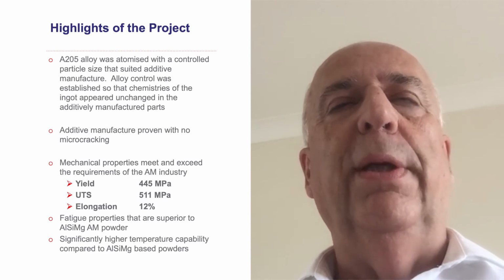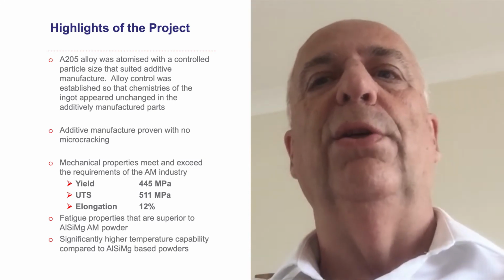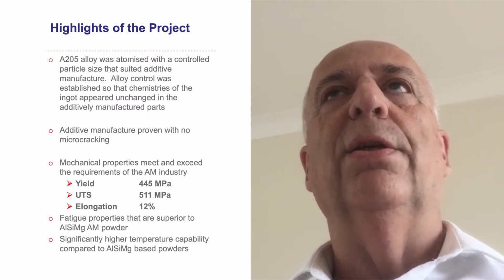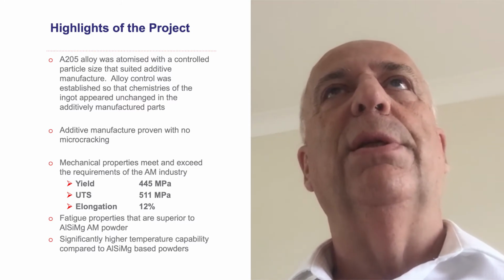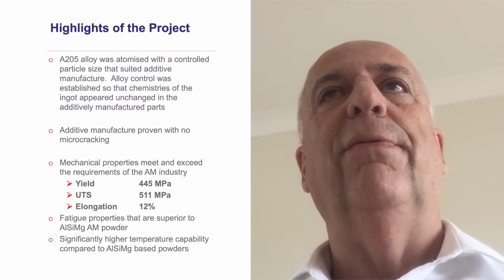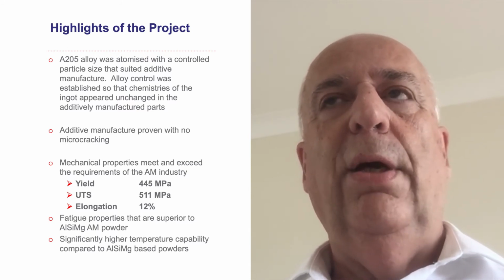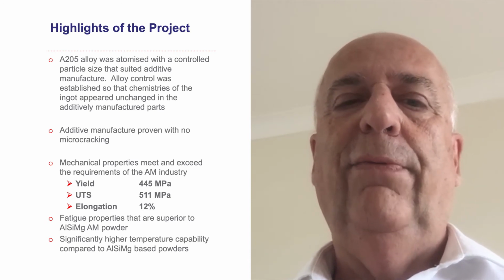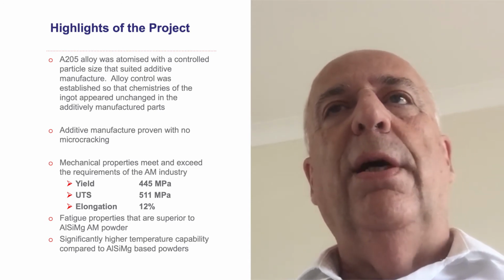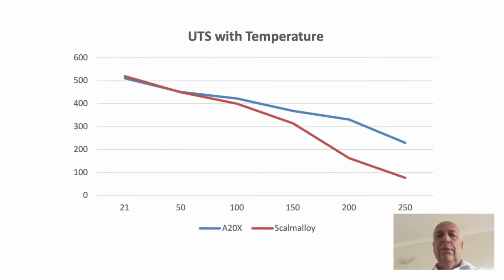And the fatigue properties that we achieved, which were measured by Rolls-Royce, were actually greater than aluminium, silicon, magnesium, the standard additive manufactured aluminium powder. So we had higher strength, better ductility, higher fatigue. And when we looked at the other significant factor that you'll need for aerospace use, which is can you run this aluminium part at higher temperatures, we saw an even more significant advantage over aluminium, silicon, magnesium based additively manufactured parts.